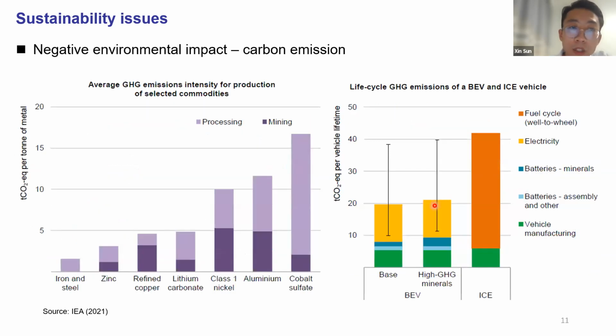Another sustainability issue for the critical materials is that the environmental impact from the mining and refining is very bad, especially for these critical materials. We need to compare these energy materials with the traditional materials, including iron, steel, and aluminum. You can see that for cobalt and lithium mining, the carbon emission in the mining stage is much higher than iron and steel.